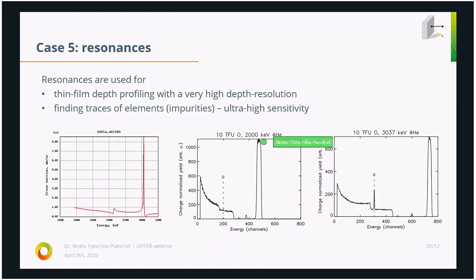This spectrum was taken at the energy of 2 mega electron volts for helium. So there is no resonance used. And as you can see, you see no oxygen signal. But if you change to the resonance energy, which is 3037 kilo electron volts, then suddenly you start seeing this oxygen. This is performed at a very exact energy, and you can see exactly where your oxygen layer is located, and how much exactly oxygen you have, very precisely.